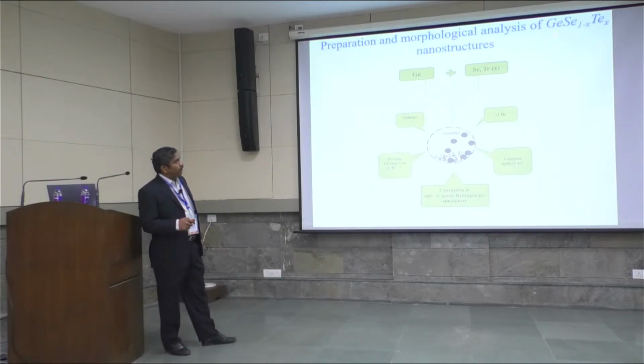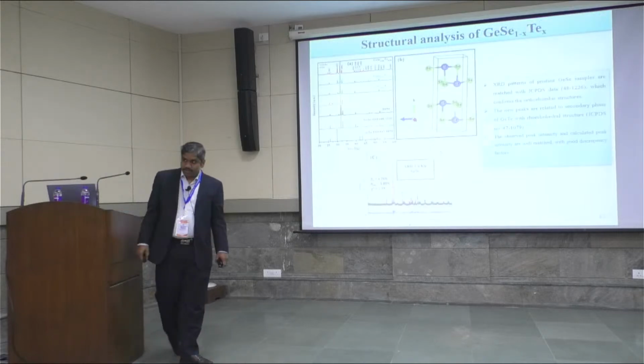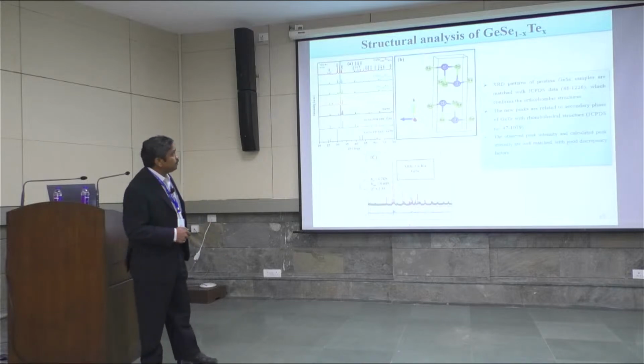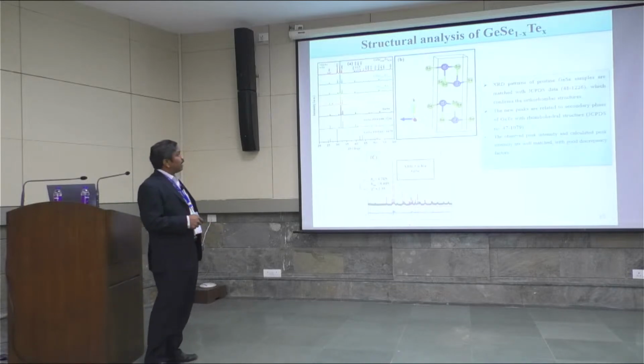And he has prepared this germanium selenide by substituting tellurium at the selenium site. They have prepared the samples by ball milling. They took the samples in the stoichiometric ratio and milled them with optimized sample-to-ball ratios. After that, they calcined the sample under a hydrogen ambient at about 400 degrees Celsius. And these are the structural features of the tellurium substituted germanium selenide.